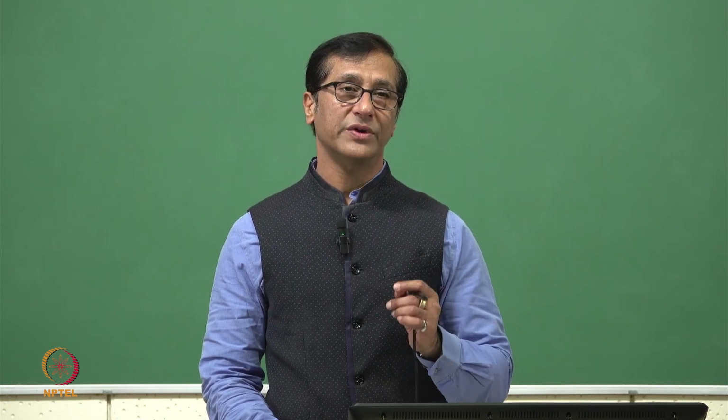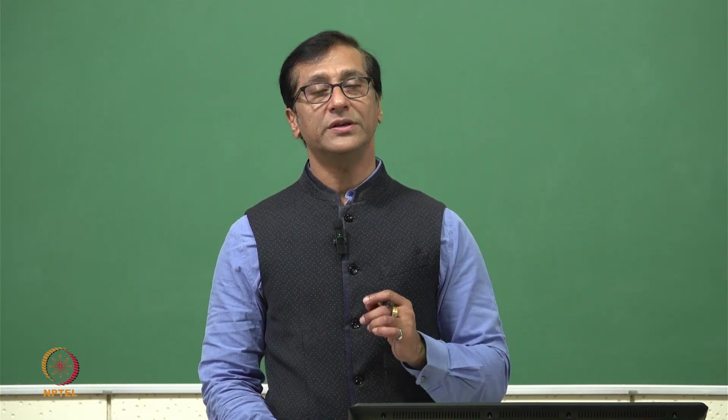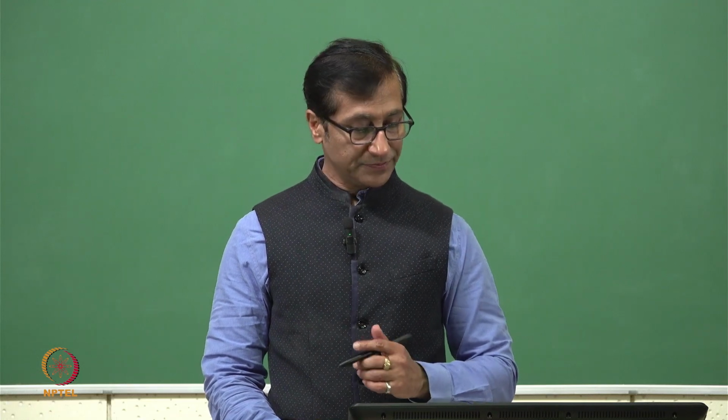So if it's 5 hours of ball milling, and I go for 15-hour ball milling, the coating which comes will have lesser porosity and the surface will be better in that case.